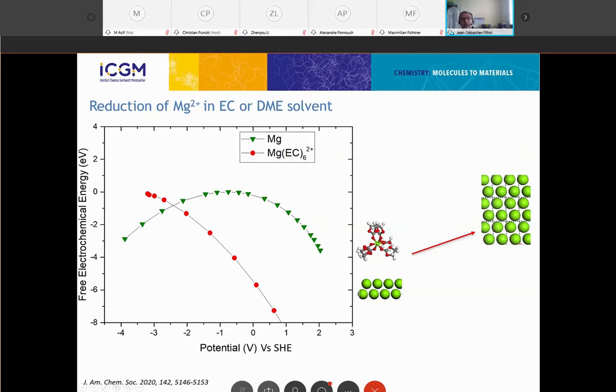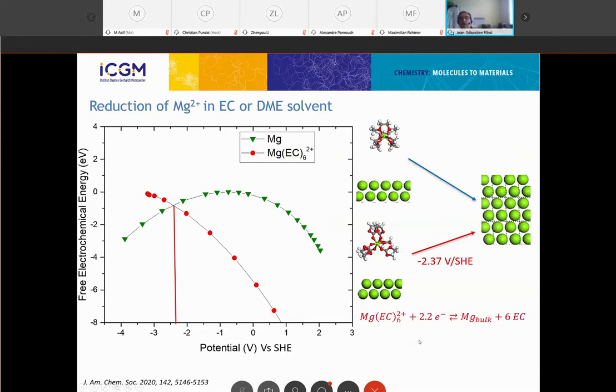We did it for two solvents, the classical one, the classical carbonates used for lithium, that we model as ethylene carbonate, that is of course not the best for magnesium, and we are able to get the reduction potential in ethylene carbonate. That will be minus 2.37 versus standard hydrogen electrode. That is very close to the experimental data that is around minus 2.4. If we look at the same reaction, we of course exchange two electrons, and we can also do that with another solvent that will be DME. And with DME, in fact, we get mostly the same thermodynamic properties for the reduction of magnesium 2+ into magnesium 0, that will be also around minus 2.4. So for the moment, everything seems okay.